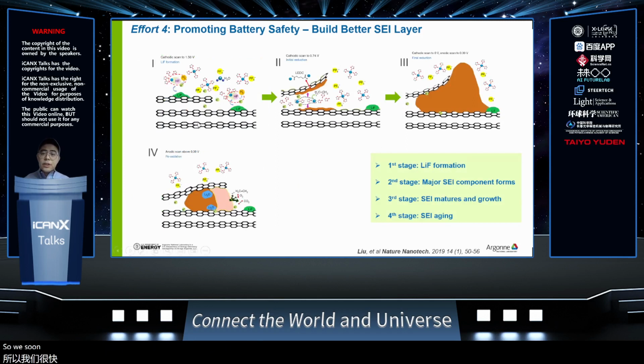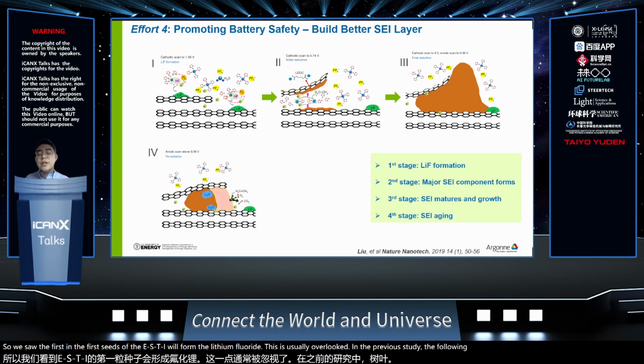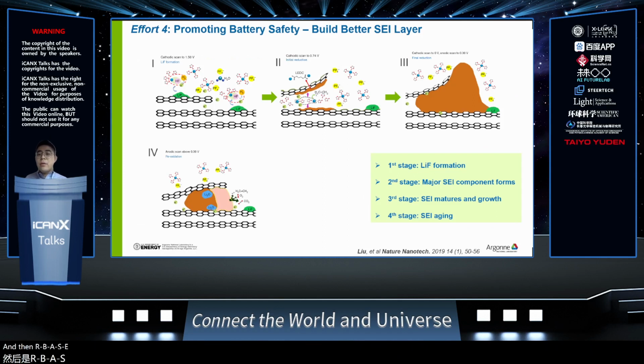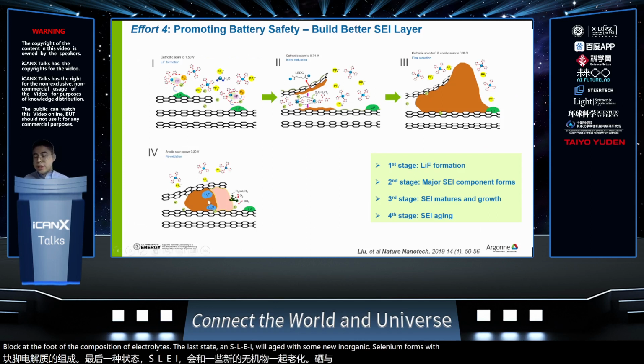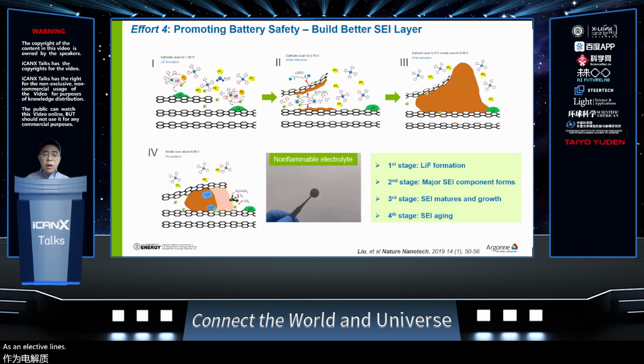We found that in the first stage, the SEI will form lithium fluoride. This is usually overlooked in previous studies. Following that, the major SEI component, LEC, will form in the second stage. Then the SEI will mature and grow thicker to block further decomposition of electrolytes. In the last stage, the SEI will age with some new inorganic components forming. With these understandings, we have developed a new series of electrolytes that are non-flammable and can build better SEIs. With these strategies, we could completely solve these safety concerns.